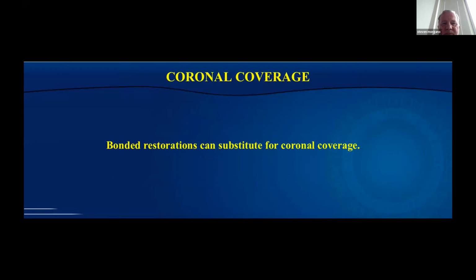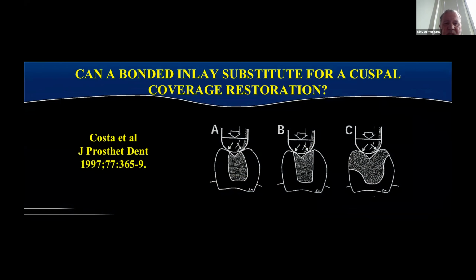Now, next statement. Bonded restorations can substitute for coronal coverage. Is that a myth or is that a reality? So this in vitro study evaluated endodontically treated extracted teeth. Group A was amalgam restoration, MOD. Group B was a bonded MOD inlay. Group C was a metal onlay cemented with zinc phosphate cement. They loaded these until failure, and the onlay cemented with zinc phosphate cement was the strongest. The weakest was the silver amalgam, and the bonded inlay was in between.